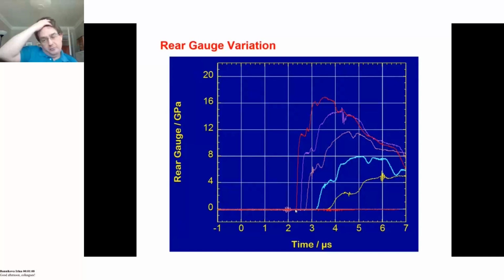So what we're saying is the transit time through that sand layer has reduced very much over that process. The other thing you will notice is there is a step followed by a second ramp, and you will notice there is some evolution of smaller features that you see on that ramp. I personally think this is due to the time taken for individual grains to fracture. However, there is no definitive conclusion on that.